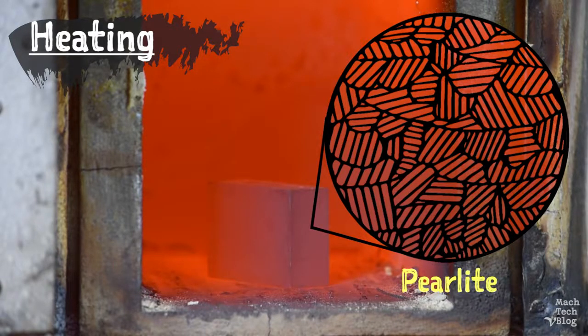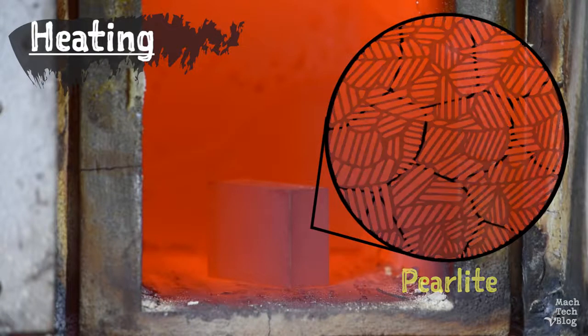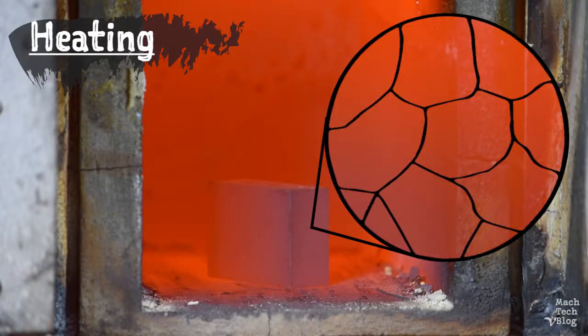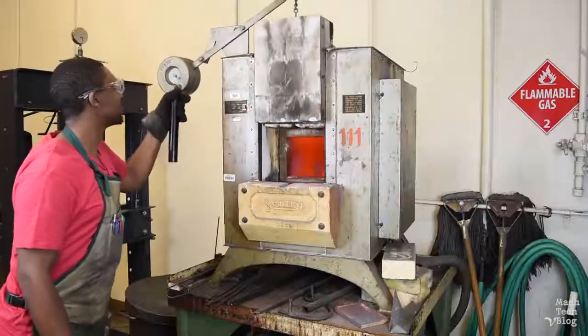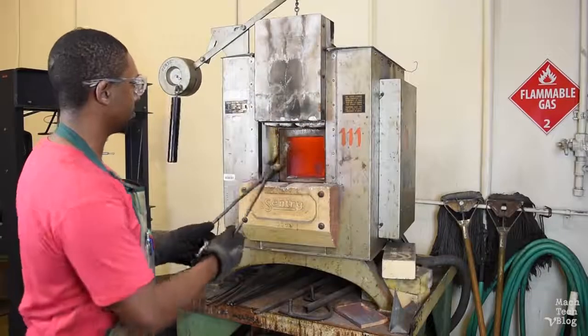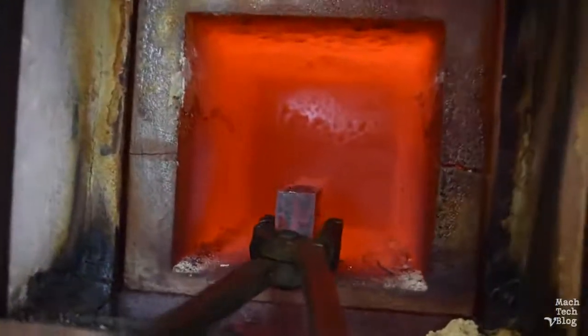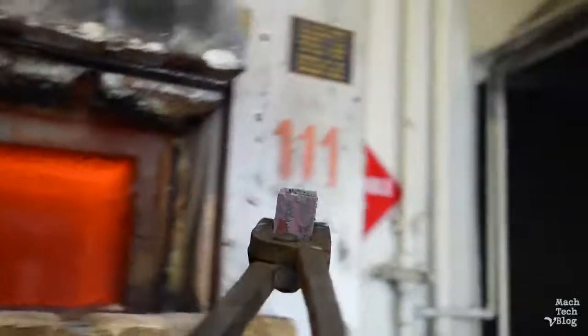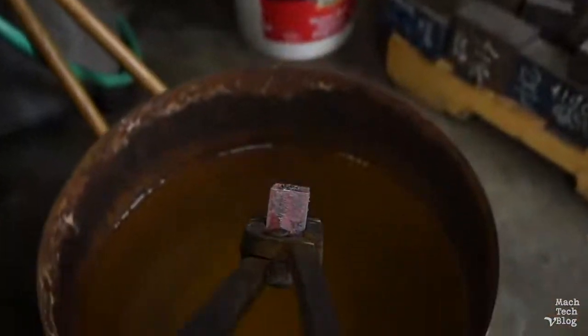When the steel gets hot enough, the pearlite dissolves and the microstructure transforms into a non-magnetic solution of carbon and iron called austenite. Once all of the pearlite is dissolved, it's time to quench. Pull the parts out with a set of tongs. Quickly plunge them into a container of water and agitate the parts in a figure-8 motion until they're cool to the touch.